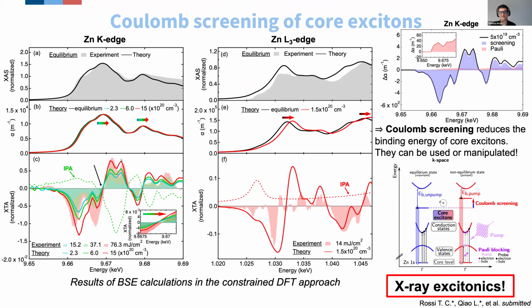I have a quick follow-up question. Thomas, you mentioned that the ability to separate cleanly starts to break down when you go to soft X-rays and you're dealing with higher level orbitals. And you indicated that you saw this. So what was the indication to you? It's simply because the theory agrees less with the experiment. So I find the calculations on the left to more convincingly reproduce experimental data than the one on the right at the zinc L3 edge, and this is basically how I explained it. That I believe that this has to do with the radius of the exciton increasing and coupling more and more strongly with the lattice heating, so that these two contributions are not independent anymore. Okay. Yeah. Thanks.